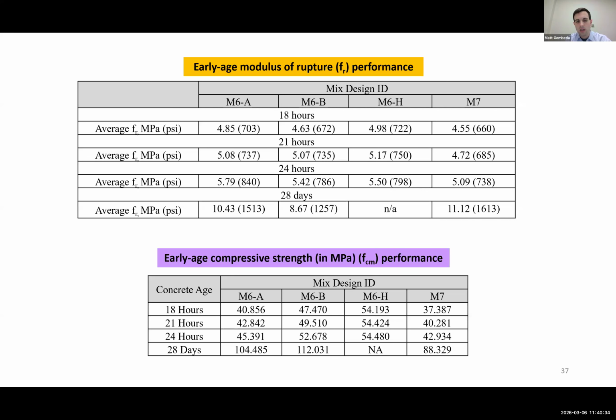Just to give you an idea of what the corresponding compressive strength was, at 18 hours we have 47 MPa, so somewhere less than 7,000 psi, high 6s, right? So we're hitting these targets that normally we would hit with much higher strength concretes, but we're in the 6 or 7,000 psi compressive strength range corresponding to these things, which shows that difference in the correlation of those 2 values.